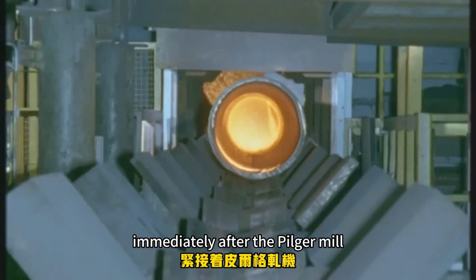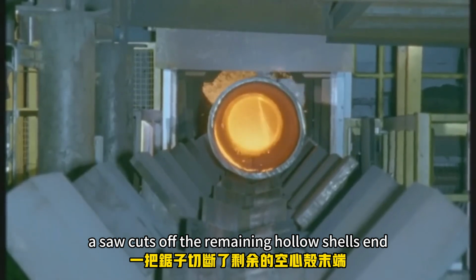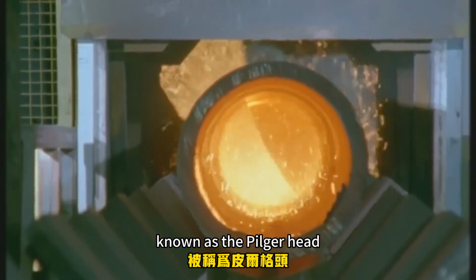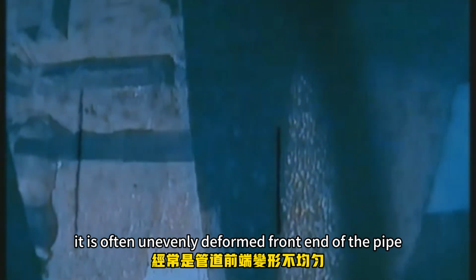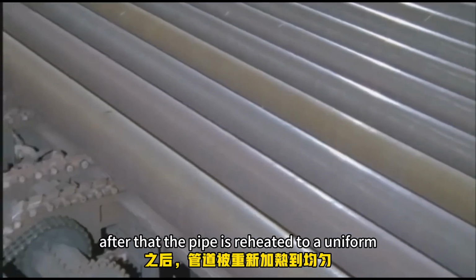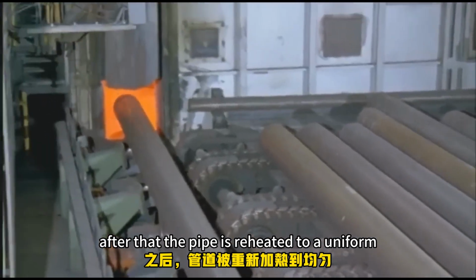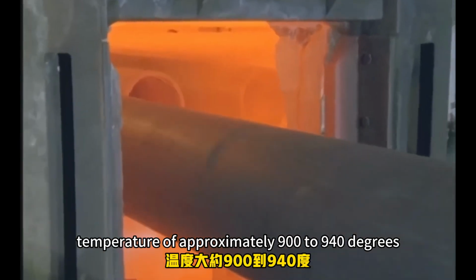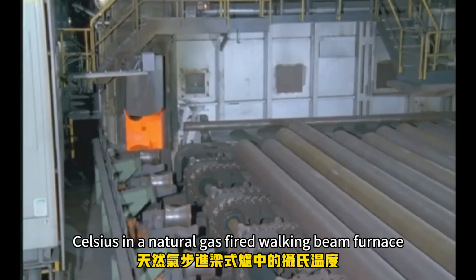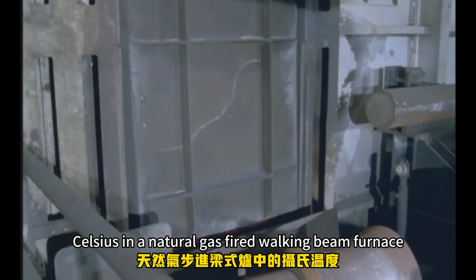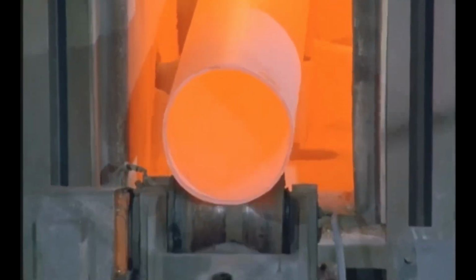Immediately after the pilger mill, a saw cuts off the remaining hollow shell's end, known as the pilger head. It is often unevenly deformed front end of the pipe. After that, the pipe is reheated to a uniform temperature of approximately 900 to 940 degrees Celsius in a natural gas-fired walking beam furnace for further processing.